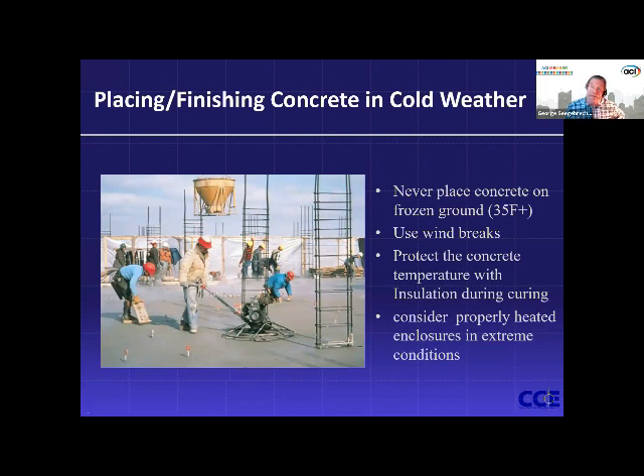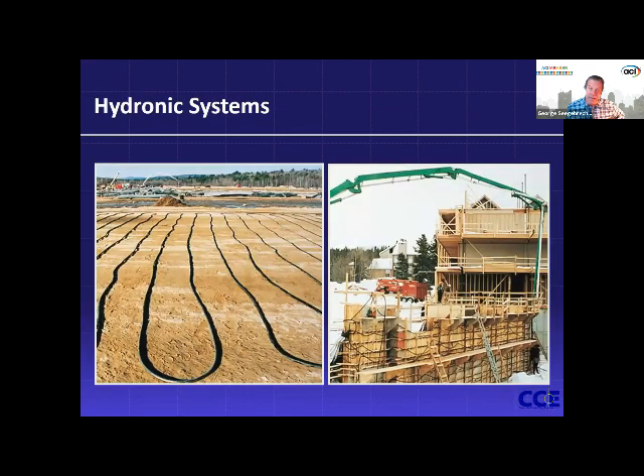So they're doing something good, but not overdoing it by capping everything off and heating everything in the enclosure on top of that. Hydronic heating systems can be used here. If you use the hydronic heating system and cover this with insulating blankets, you can keep the subgrade warm. These same kind of systems can be used on the side of walls, but you're going to, again, have to add insulation.